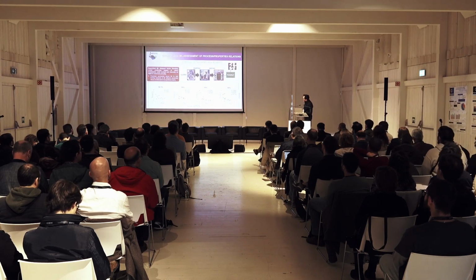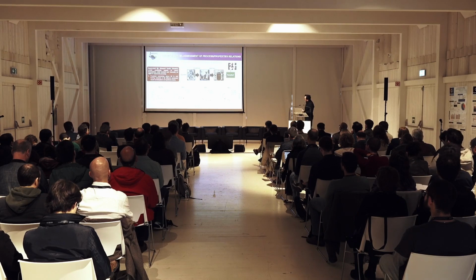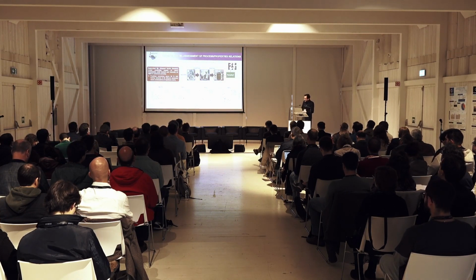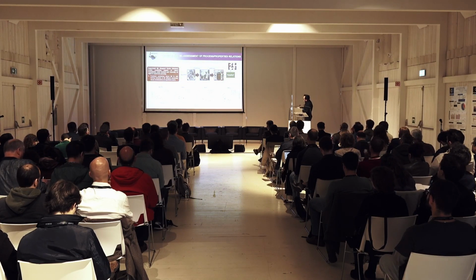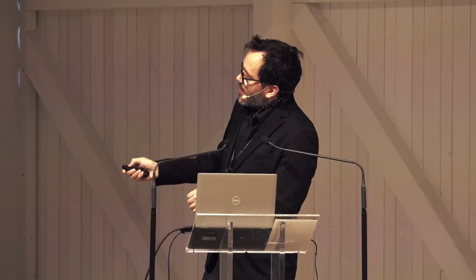The example here is regarding the application of a supervised machine learning technique called support vector machine, where we want to predict how the slurry formulation, that means the proportion of active material and carbon binder you have in the slurry, the solid content of the slurry and the viscosity of the slurry impact the electrode porosity produced with an active material. Here it's nickel, manganese, cobalt, 111 in terms of stoichiometry between the three components. So we produce a slurry, we cast it, and then we dry it, right?